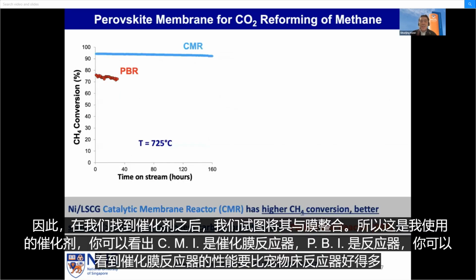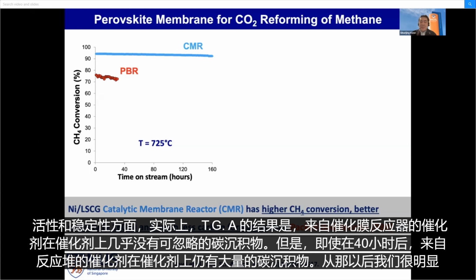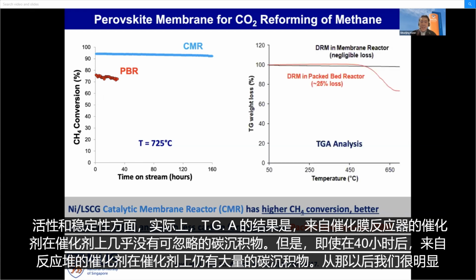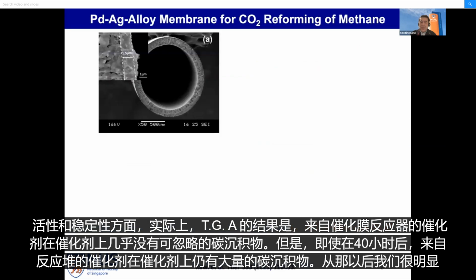After we have found the catalyst, we try to integrate that with the membrane. This is the perovskite catalyst, and you can see that CMR is the catalytic membrane reactor, PBR is the packed bed reactor. You can see that the catalytic membrane reactor performs much better than the packed bed reactor in terms of activity and stability. In fact, the TGA result shows that the catalyst from the catalytic membrane reactor has negligible carbon deposit, but the catalyst from the packed bed reactor has quite a lot of carbon deposit even after 40 hours of reactions.